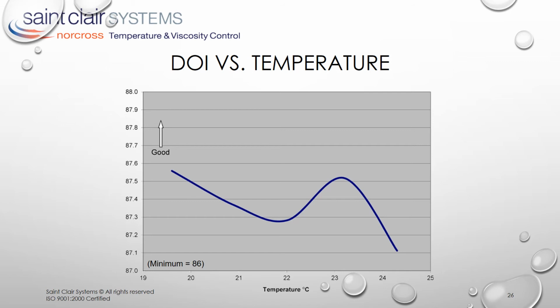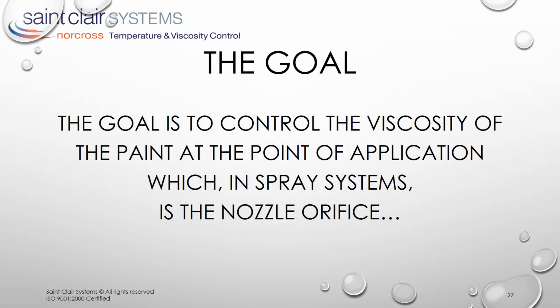The last parameter provided by the wave scan is DOI, which stands for distinctness of image. Think of this as a measurement of how close the finish is to a mirror. Here we can see that the DOI remains above the 86 minimum value throughout this entire temperature range, and therefore is not of concern when optimizing shortwave and longwave performance. The goal, then, is to control the viscosity of the paint at the point of application, which in spray systems is the nozzle orifice. And it doesn't matter whether you're using a gun or a bell, but that's a topic for a whole separate presentation.